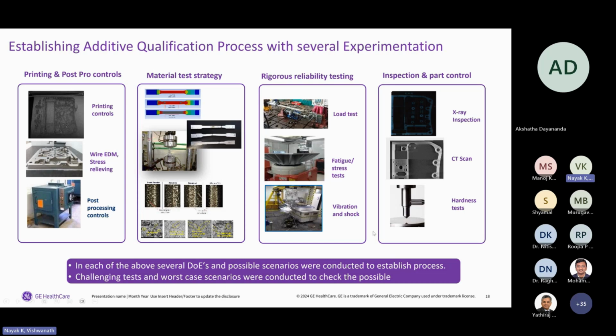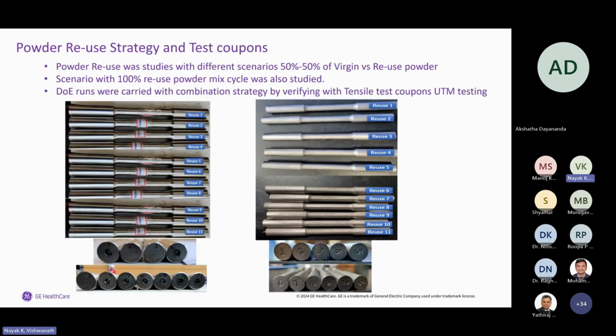And then, when each component goes for production, every component is tested for hardness, with ball indentation testing. So for each of the cases, different scenarios were established, and we figured out how we can control and consider the outer bounds in all the different parameters, and then see how our DOEs look and where we would be with different variations. And then there were also some challenging tests and worst case scenarios conducted over and above this. So this is one example of the powder use strategy I was talking about.